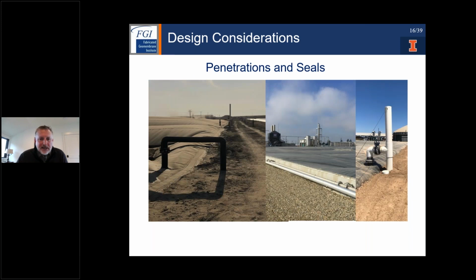Also, from a functional standpoint, you've got many penetrations of these cover systems, and you want to make sure that the seals are adequate. If it's pipe type penetrations, as the outer two photos show here, simple booting systems and welding will usually do the trick. But it needs to be flexible enough. Remember, these covers are very prone to movement under wind and operational pressure, so you need to make sure whatever booting system is used there is flexible enough to accommodate that movement.